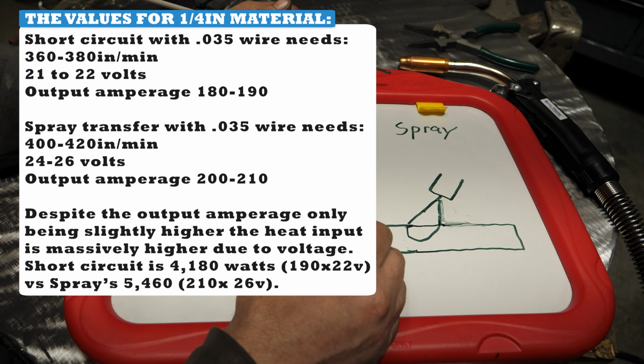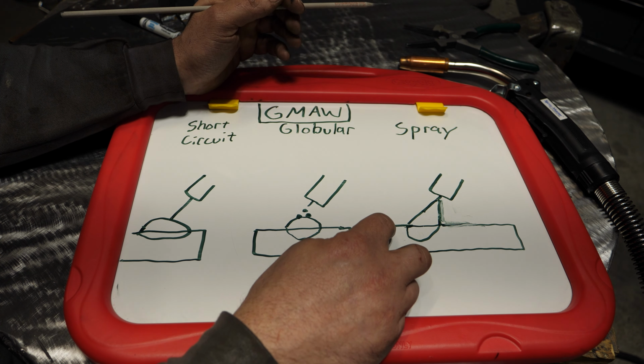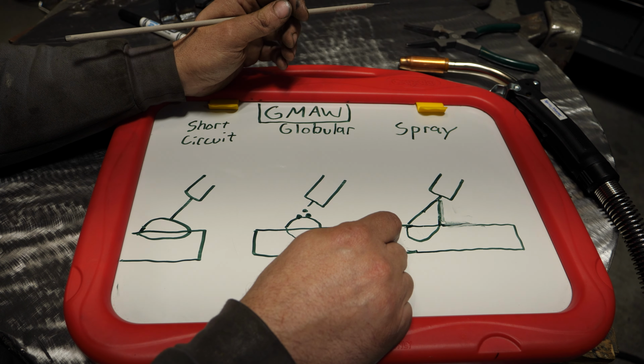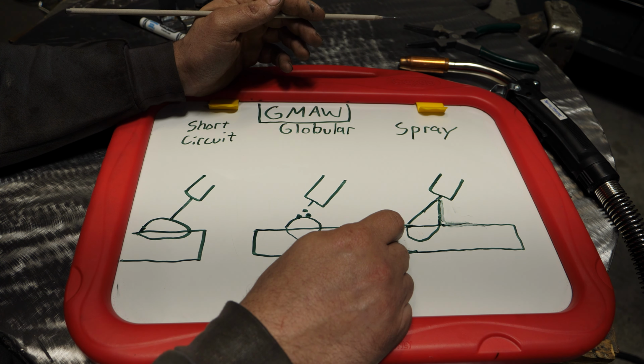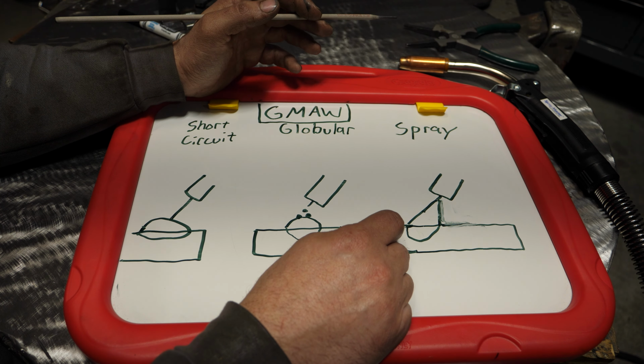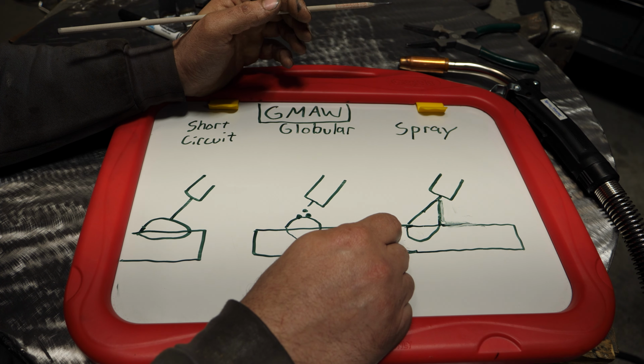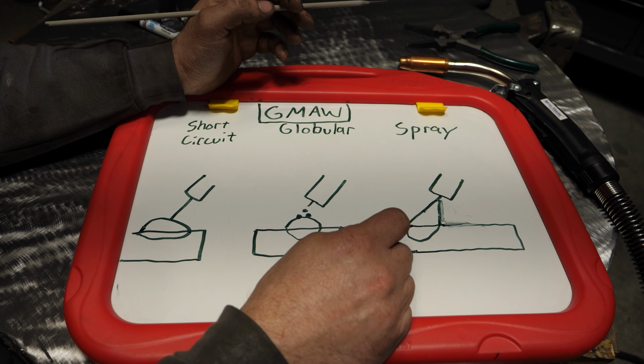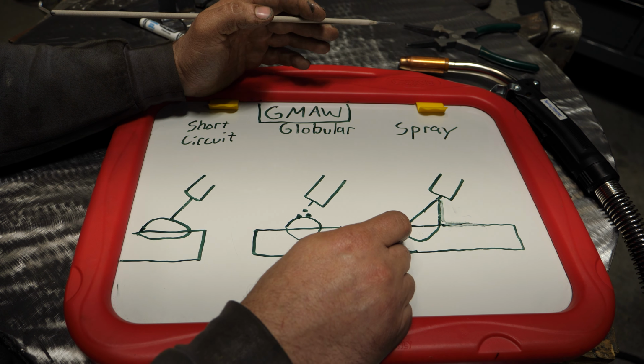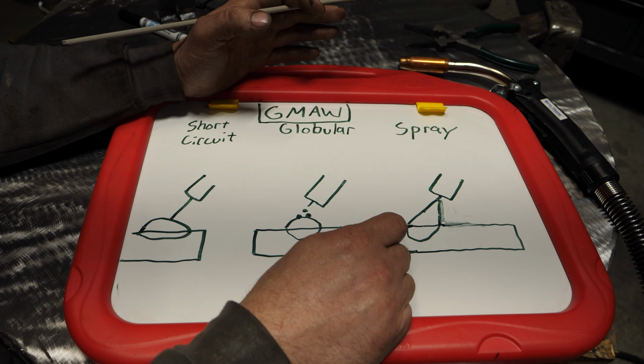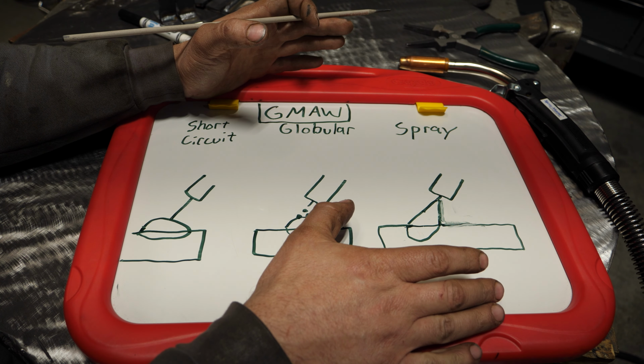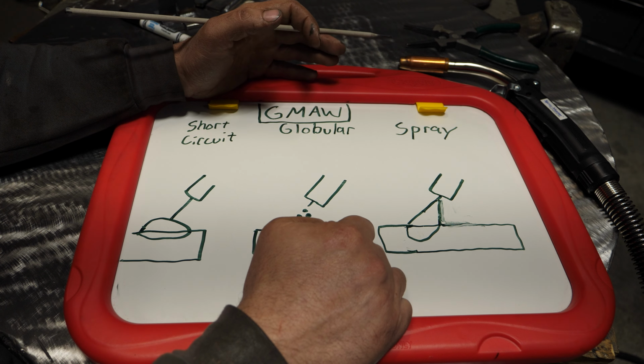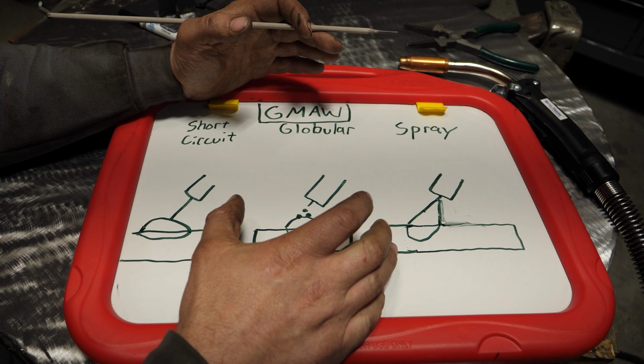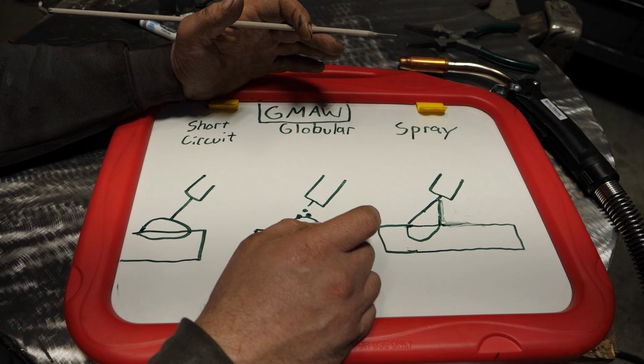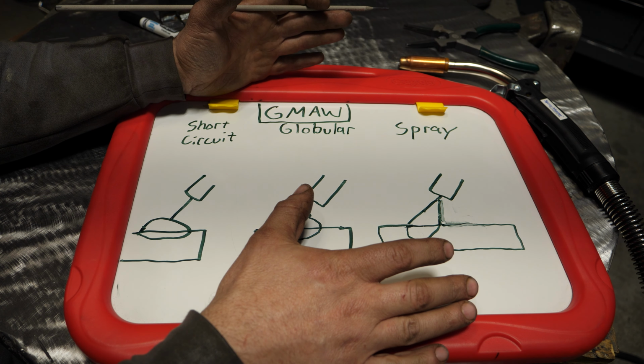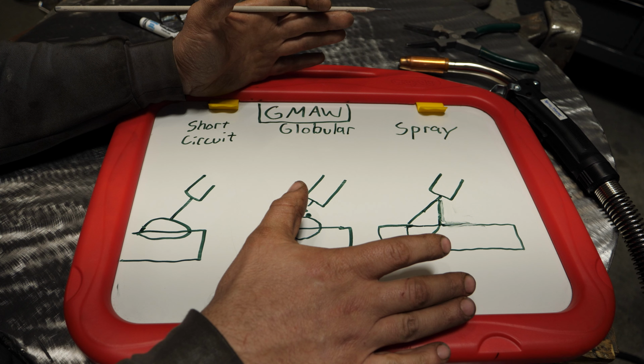Now, spray also requires special shielding gases. Universally, C25 will not work unless you put a tremendous amount of power and voltage behind it. So C10, which is 90% argon, 10% CO2, will work. And there's all sorts of other mixtures, including some with oxygen and hydrogen, that will also help a welder get into spray transfer mode. And I'm going to show you through arc footage the exact difference, and this will all make 100% sense because you'll see firsthand what's actually going on.